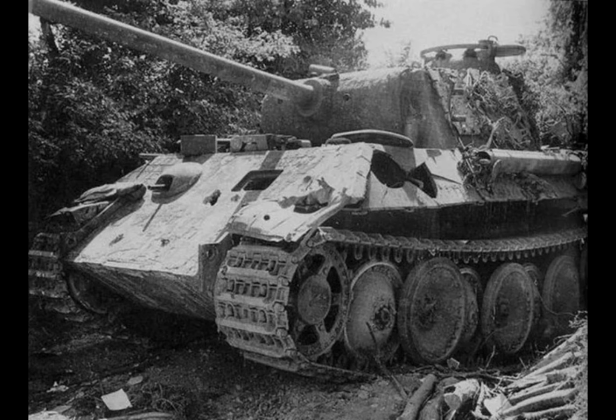German armor also suffered from inadequate heat treatment as fuel shortages limited furnace operations and Allied bombing disrupted facilities. Panther tanks produced in late 1944 frequently had glacis plates with inconsistent hardness across their surface. The center might be properly hardened while edges remained too soft, or the reverse, with over-hardened edges that shattered on impact while the center performed adequately. This inconsistency resulted from interrupted quenching procedures, where plates were lifted in and out of quench tanks multiple times, instead of being submerged continuously. The technique saved fuel, but created metallurgical problems.